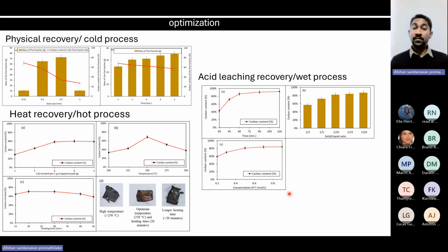But surprisingly, if I'm going to use aqua regia, since it contains less nitric acid and more hydrochloric acid, the amount of nitrogen dioxide that I'm going to emit is going to be quite lower. And also I could do the leaching at room temperature. This is the main thing, because I'm not going to use elevated temperatures, which is going to reduce my impact drastically. So this is why I have to opt for aqua regia.